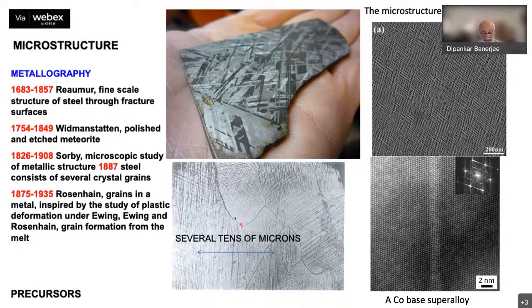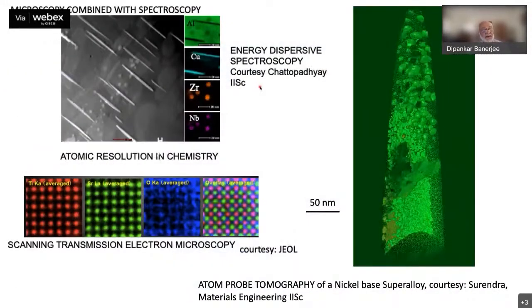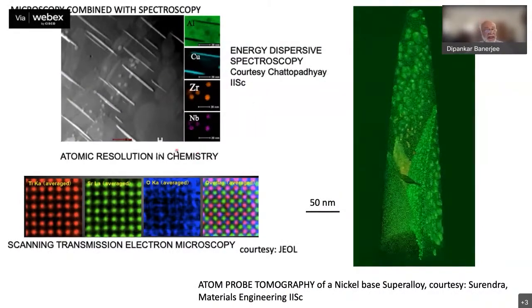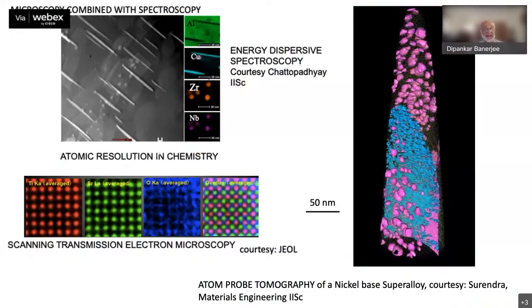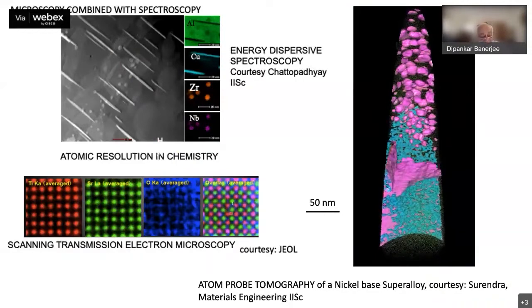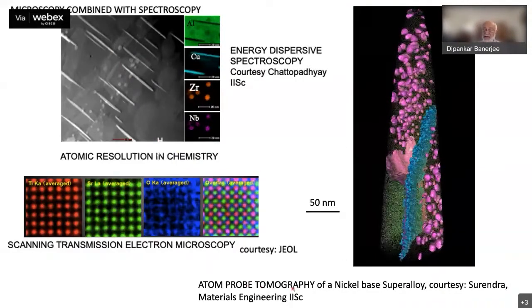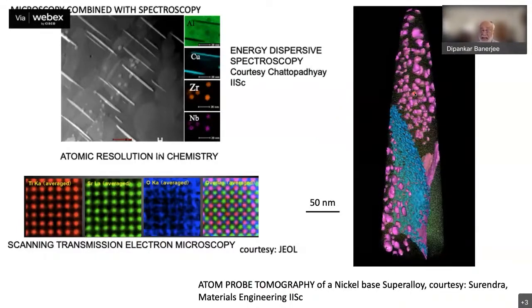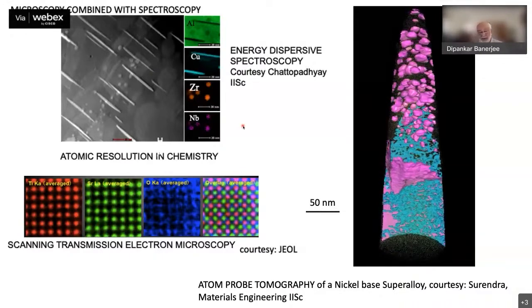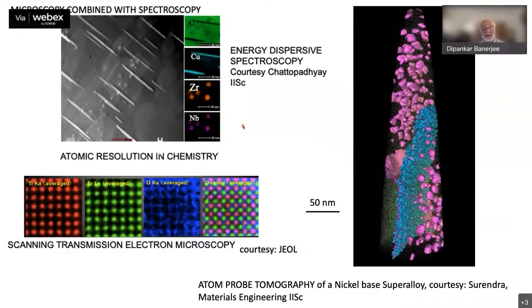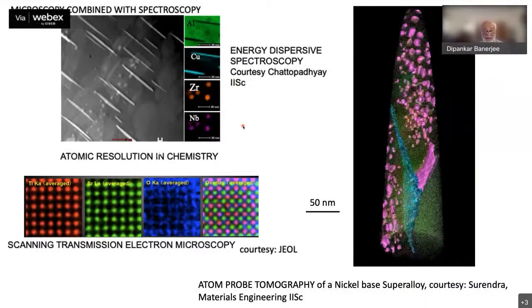And so you can see today structure at the scale of tens of microns, which could be the grains in the material. You could see the distribution of crystallites within grains, which could be as fine as 10 to 100 nanometers. You can even today, with modern techniques, see the distribution of atoms within these crystals. So we can see structure at different length scales. We can also see structure when we combine microscopy with spectroscopy. We can see chemistry at this nanometric scale. So we can see the chemistry of individual crystals. We can see the chemistry actually of individual atoms. And through atom probe tomography, we can see distribution of chemical elements in a three-dimensional sense. And so this very important evolution in our capability to look at what we call microstructure is an important part of the material science paradigm.